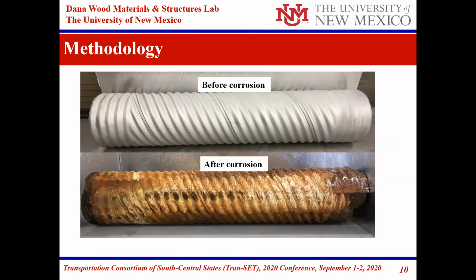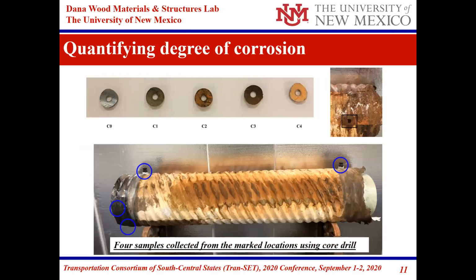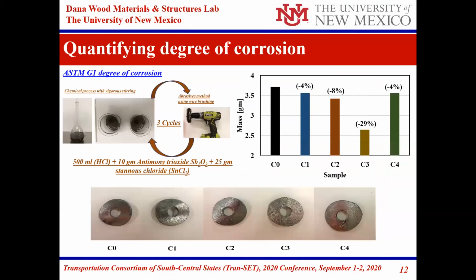So we needed to quantify the level or the degree of corrosion. So we took different cutouts of those pipes, from different places, and you can see here different levels from C sub 0 to C sub 4. We collected them, and then we used ASTM G1 to quantify the level of corrosion. You can see there is a standard procedure in the ASTM to actually measure the level of corrosion.